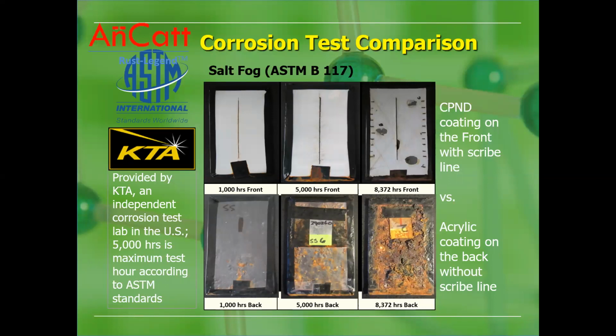The top row 3 photos are AnCatt coating with a scribe line, compared to the bottom 3 photos, which are the back of the same panel, protected by standard acrylic coating. As the corrosion test progresses from 1,000 hours to 8,000 hours, AnCatt coating on the top remained intact, while the bottom coating became terribly corroded. And after 8,000 hours of test, AnCatt coating can still provide perfect tape adhesion. That's another miracle. Please notice the scribe line remains the same width without rust expansion, which demonstrates the amazing self-sealing feature.